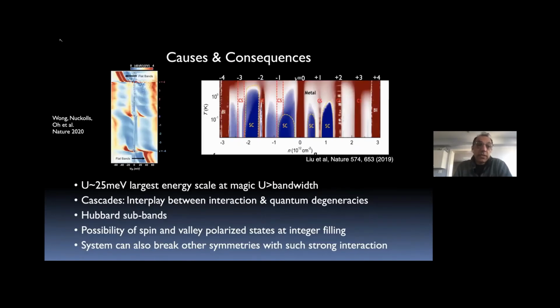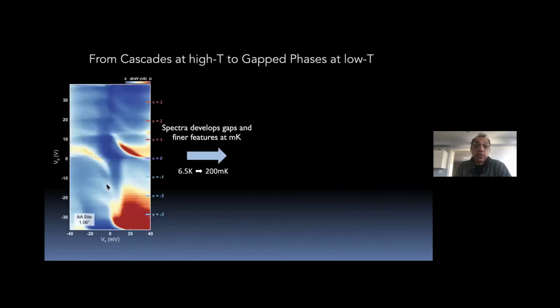So the relationship between this cascade of features in the spectroscopy and what you heard in terms of the cascades of correlated insulating phases is very clear. These large U features signal that the system has a Hubbard band-like model, where these Hubbard bands develop a sort of spin or valley polarization. Even at very high temperatures, perhaps the system knows about the fact that it wants to go into some sort of correlated state where the Hubbard subbands are separated, and you are likely making a spin or valley polarized state, some of which I'll show you as we go along. So these signatures of correlations are now becoming very quantitative with these experiments. Because now we can measure the addition and removal spectra and really establish that U is indeed larger than the bandwidth and is of the order of 25 milli-electron volts.